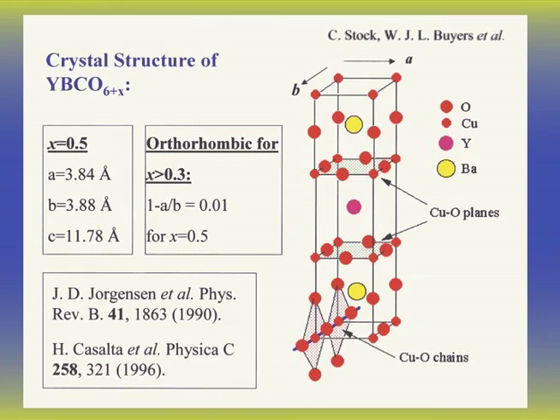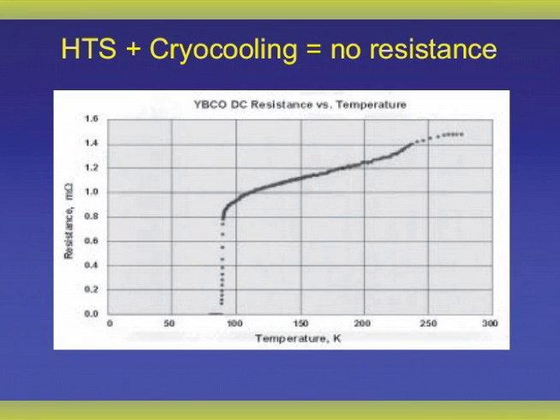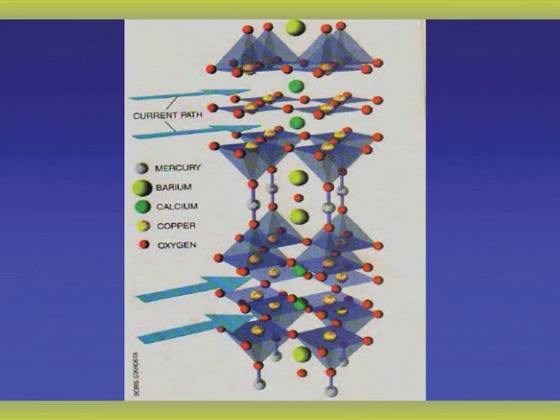And this is the material which has the highest transition temperature, which is, instead of lanthanum copper oxide, mercury copper oxide with a little bit of barium and calcium mixed in. And under pressure, this material conducts electricity perfectly at all temperatures below 168 Kelvin, which is truly extraordinary, compared to the original 4.1 or 4.2 degrees of mercury as discovered by Kamerlingh Onnes.